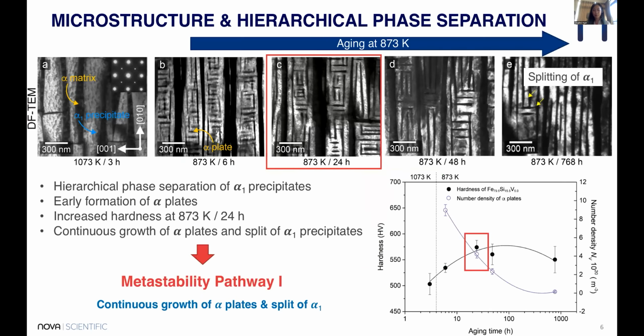This iron silicon vanadium alloy shows a two-phase structure after initial aging, where ordered alpha-1 precipitates, here in white, are embedded in a solid solution alpha matrix shown dark. When this material is further aged at 873 Kelvin, a maze-like hierarchical microstructure appears, and the additional hierarchical plates are also alpha phase. During aging, they continuously grow and eventually split the alpha-1 precipitate, which means that this alloy follows metastability pathway 1. The alloy shows the highest hardness after 24 hours of aging, which is marked by a red box here.